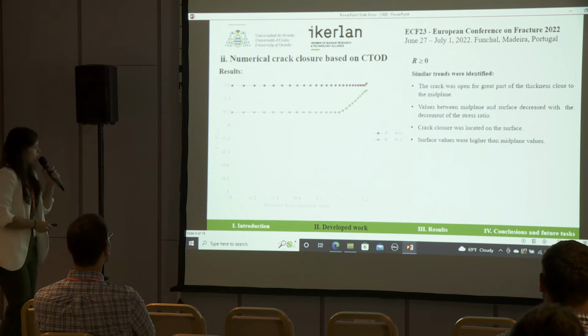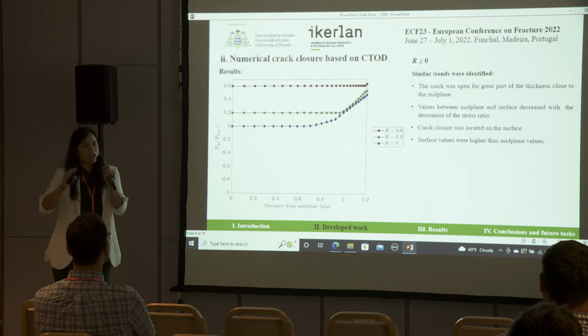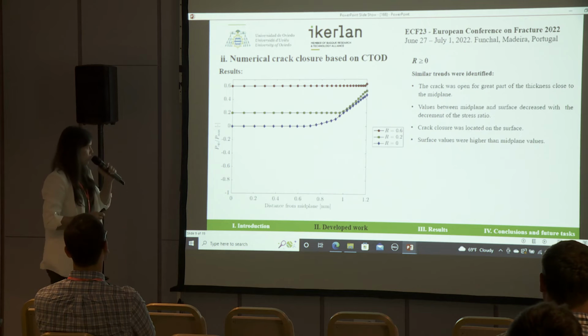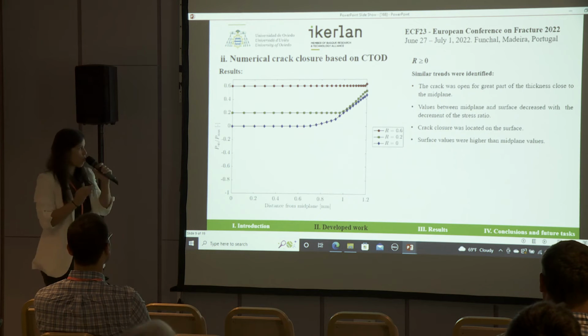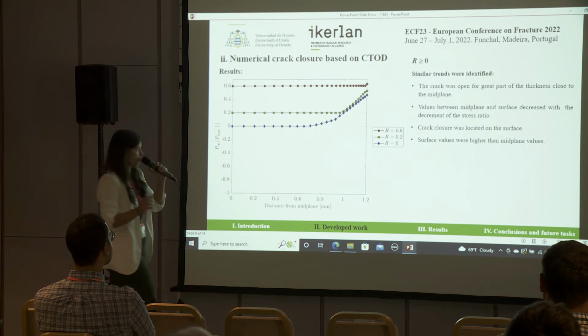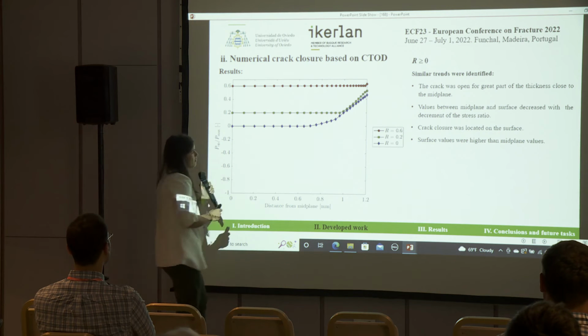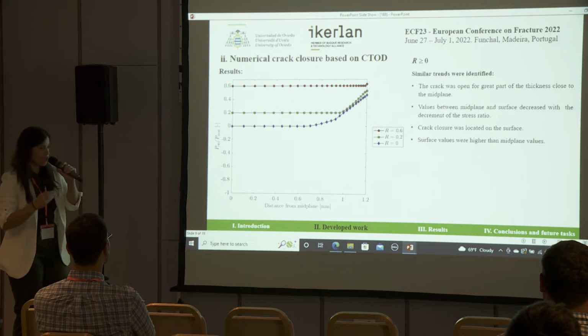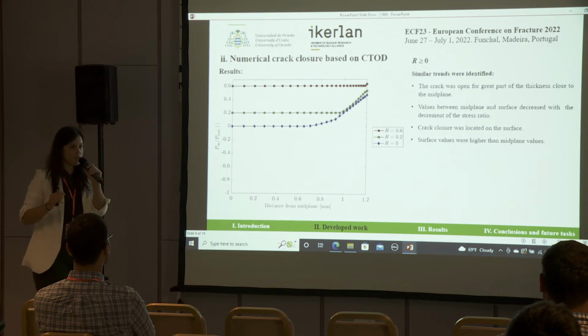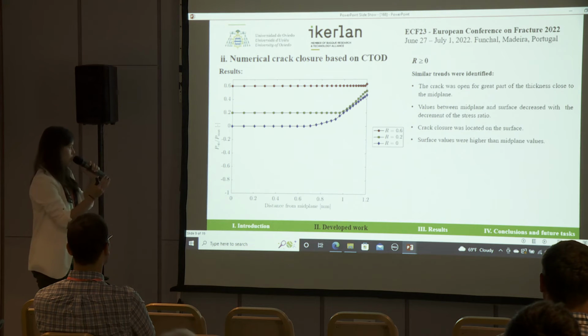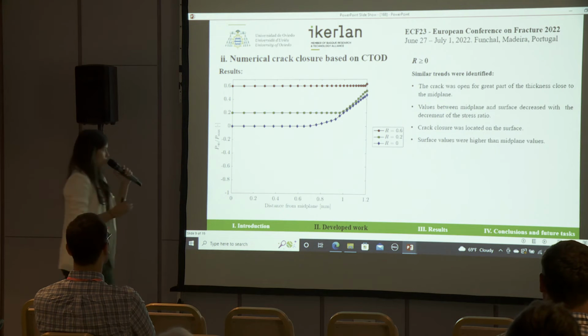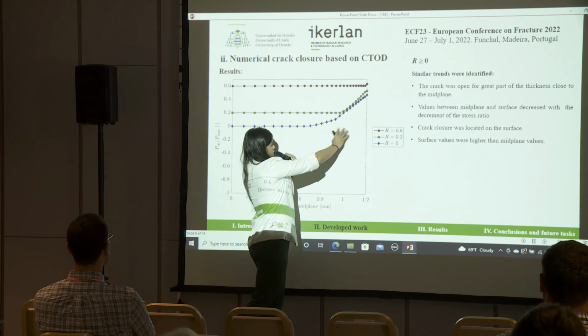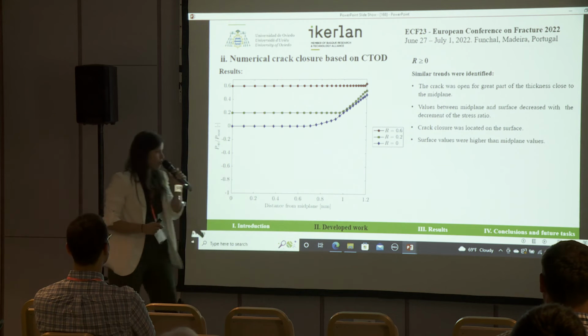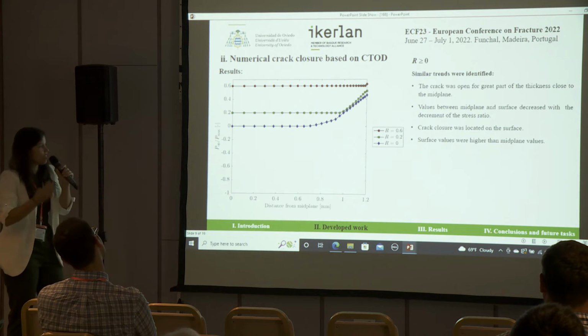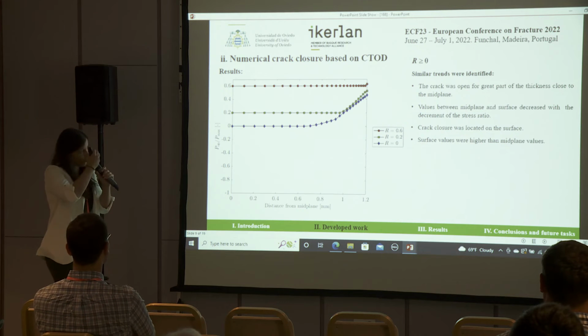So, moving on with the results, on the one hand, for positive stress ratios, similar trends were identified. First, the crack was open for a great part of the thickness close to the midplane. Moreover, the values between the midplane and the surface decreased with the decrement of the stress ratio. The crack closure was located on the surface here, and the surface values were higher than the midplane values, according to the previous work.